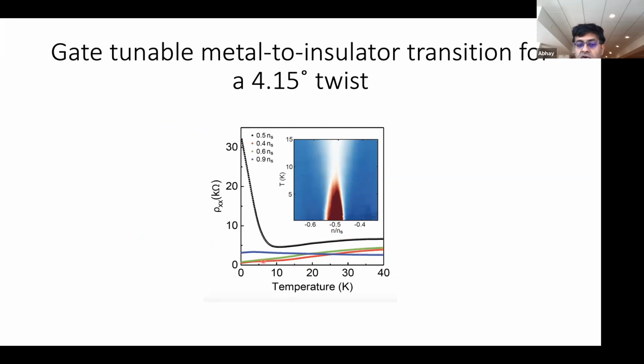And here are shown a few of the actual traces of resistivity as a function of temperature, where you can see that if you're sitting exactly at half filling, then you go from something that's weakly metallic to insulating behavior with a fairly well-defined transition temperature.